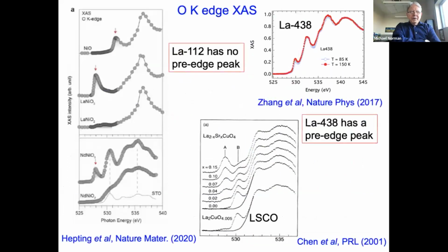As was noticed early on by Matthias Hepting, if you look at lanthanum 112, it has no pre-edge peak at the oxygen K-edge. But then again, LSCO doesn't have a pre-edge peak in the insulating phase either, and you have to dope to get a pre-edge peak to show up in the oxygen K-edge, which would indicate the participation of oxygen holes. I contrast this with what we saw in the reduced trilayer nickelate, where you actually have a pretty pronounced pre-edge peak at the oxygen K-edge for this lanthanum 438 material.